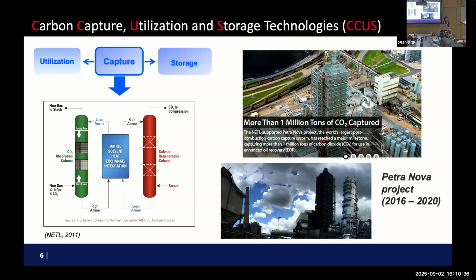So amine was something in between that's strong enough to bind, but weak enough to release at 120 to 160 degrees C, which is around the temperature where we can still use waste heat to release. That's why there was a forward concept of it. So after studying for many, many years, finally in 2016 in the United States, we started to scale up to a much larger scale. This is near Houston, called the Petra Nova project, in one of the power plants.